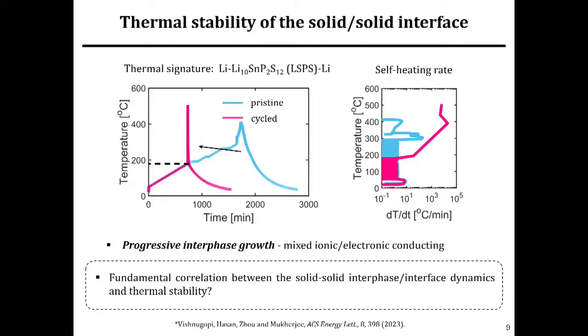We see that there is a drastic change in the thermal signature of a pristine versus a cycled cell. This is because of the chemical interface that continuously keeps evolving at lithium metal and solid electrolyte interfaces, which confirms our hypothesis that safety is not guaranteed in such non-flammable solid electrolytes, and rather it requires a detailed mechanistic interrogation. I'll stop here because this work is also presented in one of the posters today, so you can learn more about that during the poster.